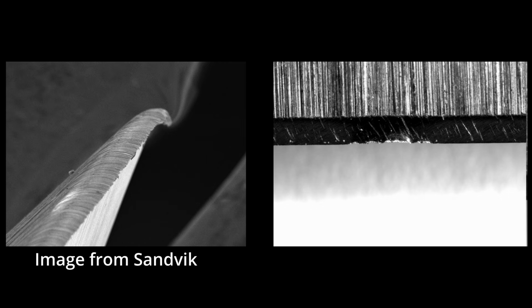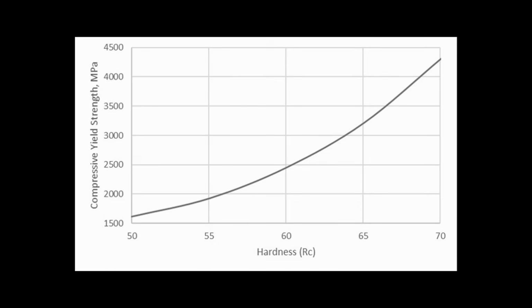Another common way that steels lose sharpness is through deformation. The edge will literally fold over or mushroom during use. This is of course most common with thin edges and high forces being applied. So this will depend on the type of knife, the user, and the specific thing being cut and in what way. Hardness correlates very well with strength, and strength is essentially the measure of resistance to deformation. So a steel with high hardness is more resistant to deformation.